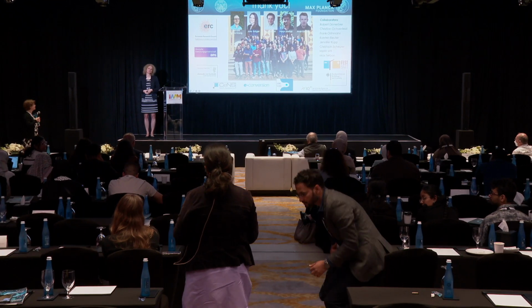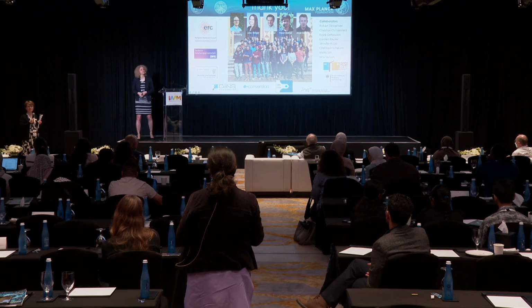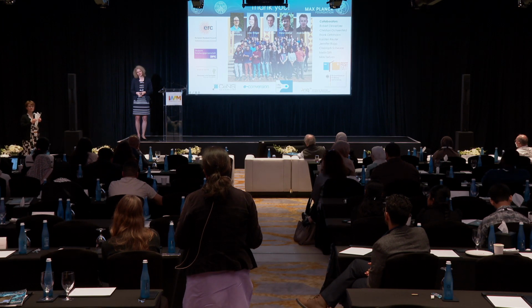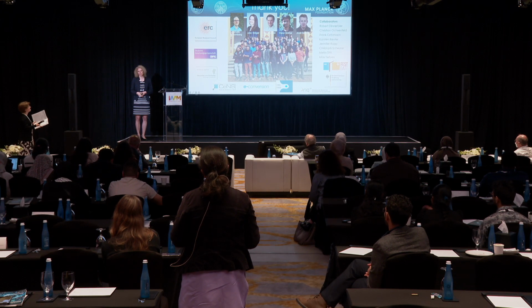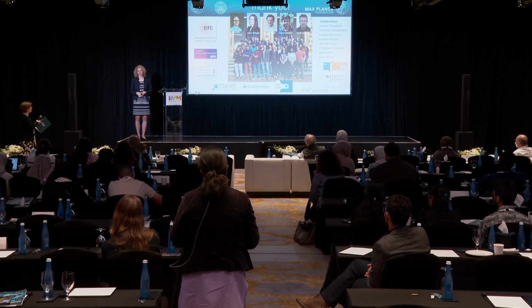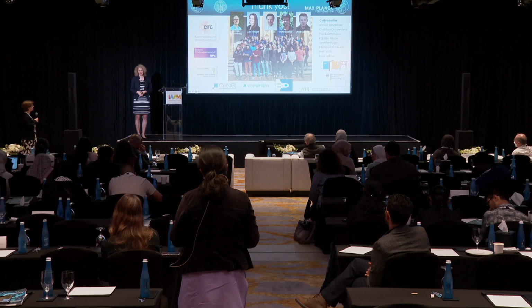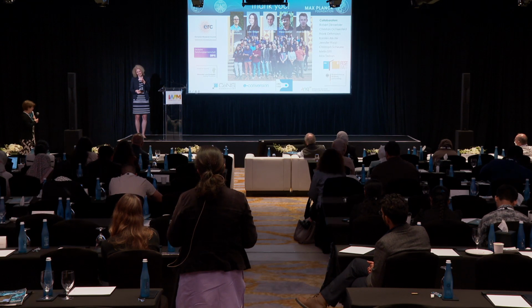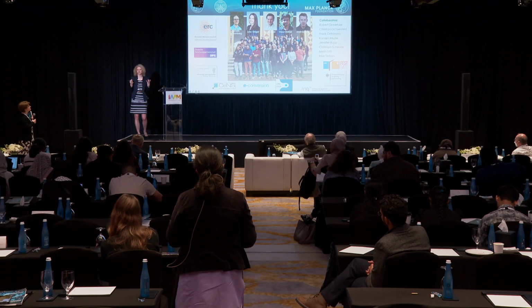Bettina, very nice talk, very interesting talk. I was just wondering, when you're doing these solar batteries, what's the time scale of charge separation that you're talking of? So charge separation is actually very rapid. It has to be because recombination is fast on the nanosecond time scale. So simply judging from the natural charge recombination that we see in the system, it is rapid, but this is exactly the reason why we add the separator, F8BT, which prevents the naturally occurring charge recombination.